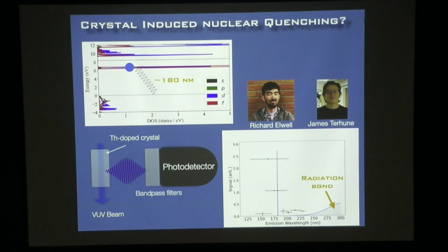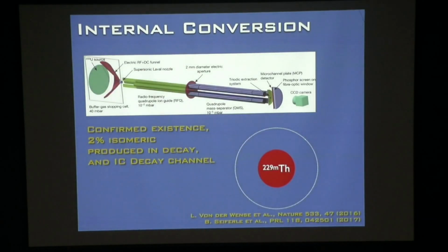But what they then saw was a very narrow peak, somewhere around 180 nanometers, which is right around where the DFT calculation is. So at this point in time, we were starting to think, hey, this idea that we've been pursuing for over a decade will just never work. That generically you're going to have these defect states, there's going to be this quenching, and this whole crystal approach won't work.